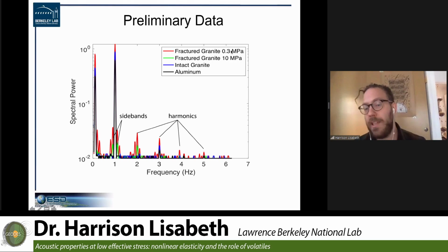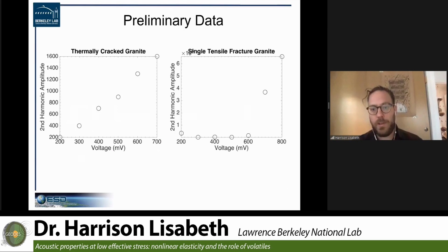And at low effective pressure, so that tensile fracture is somewhat open, you get substantially higher sidebands. You see this is a log scale, so there's a pretty dramatic increase in the amount of sideband energy that you get. And you also get the generation of more harmonics and even some harmonics of the sidebands themselves. And so you can use the harmonic amplitudes as a function of strain, here as a function of drive voltage, which is a sort of proxy for strain, and see that you get different signals for different structures of damage within the material.